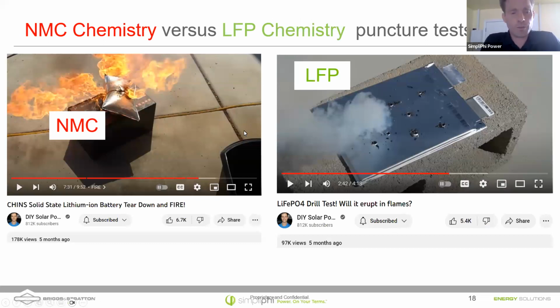Here are two pouch cells. These are comparing NMC chemistry, and there is a place for NMC chemistry. If you're building something that needs to be lightweight like a drone, you're going to need to use a lighter chemistry. But note that there's a much greater fire hazard for NMC chemistry. So what I'm showing you here is Will Prowse from Do It Yourself Solar. He punctured two different cells, one an NMC cell and another an LFP cell. When he punctured the NMC cell, within seconds, it starts off-gassing due to the short circuit. So he actually drilled a hole in it, right? And then it bursts into flames within about 15 seconds.